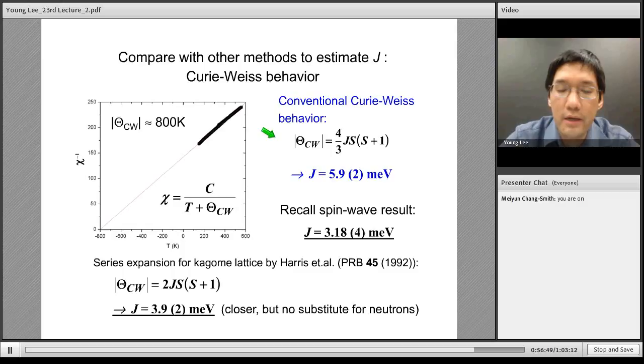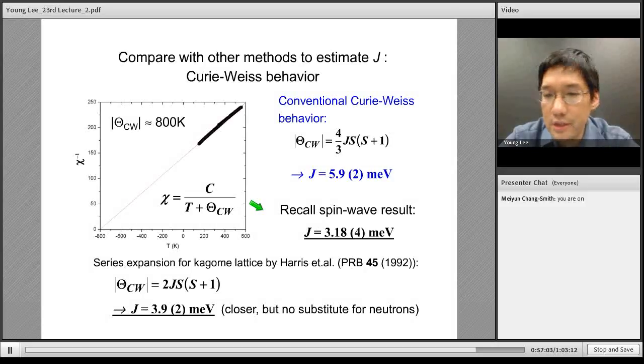So that temperature is given by the following: 4/3 J S times S plus 1. And we would have extracted a J, nearest neighbor exchange, of 5.9 meV. But we have this neutron scattering, which tells us J is actually closer to 3.2. So just doing some simple analysis of the uniform susceptibility actually gives us a substantial error in the expectations for J. It turns out because this is a highly frustrated system, there will be modifications to the susceptibility at these temperatures. We're really not in the extremely high temperature limit, so there are some correlations here, but we still get Curie-Weiss behavior due to the frustration.